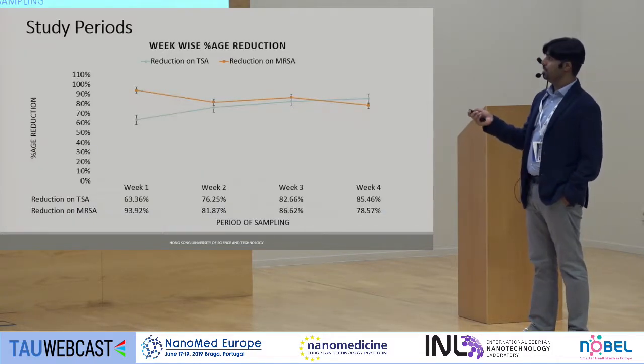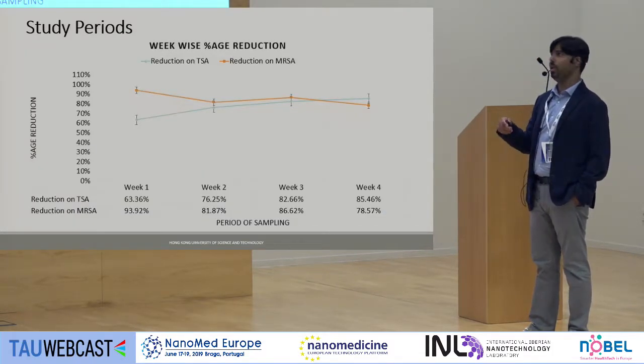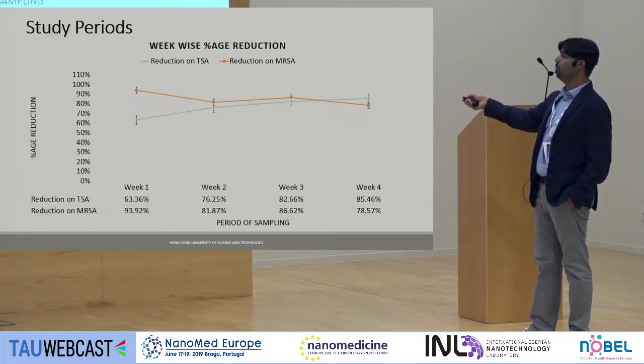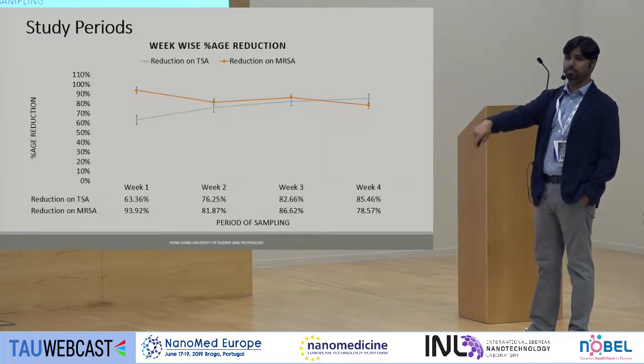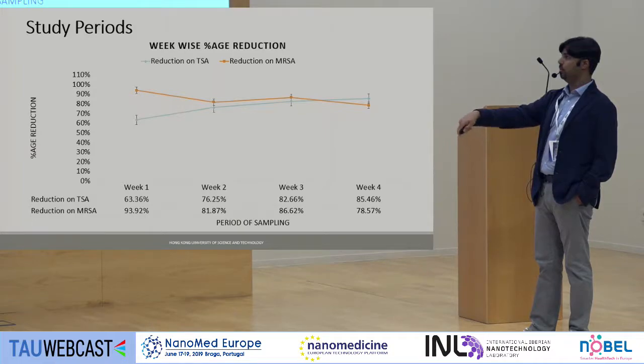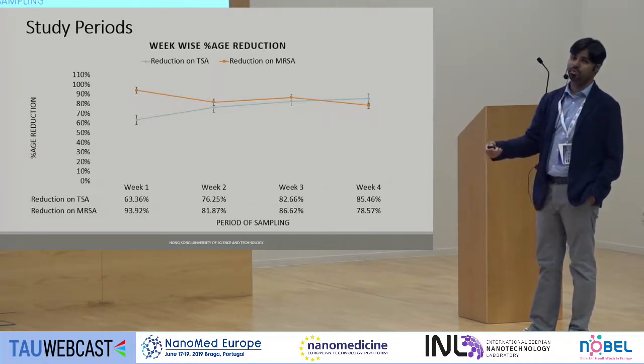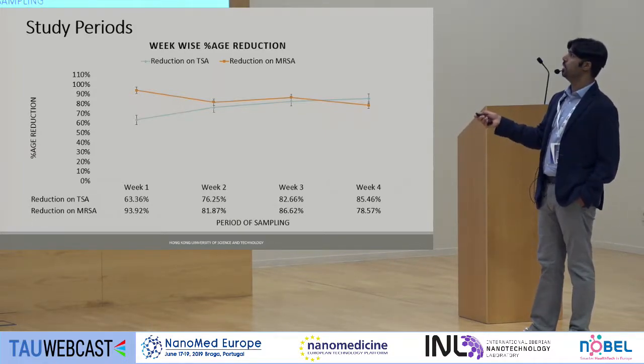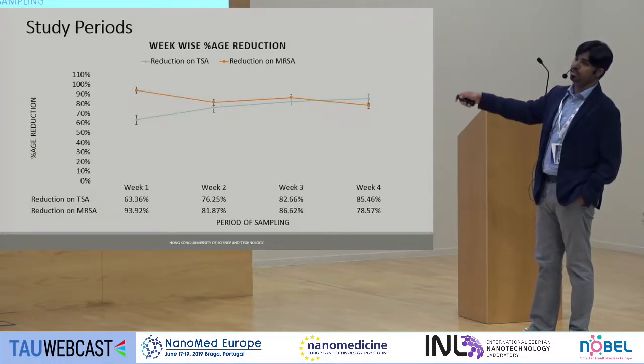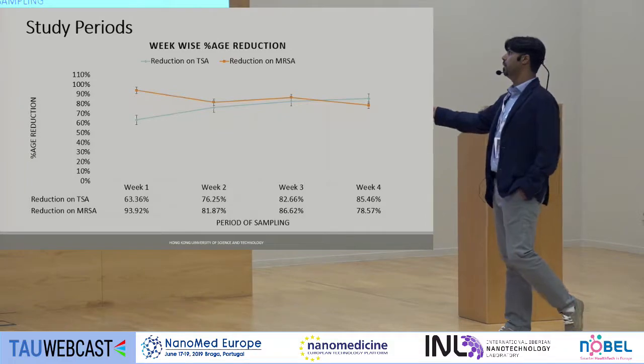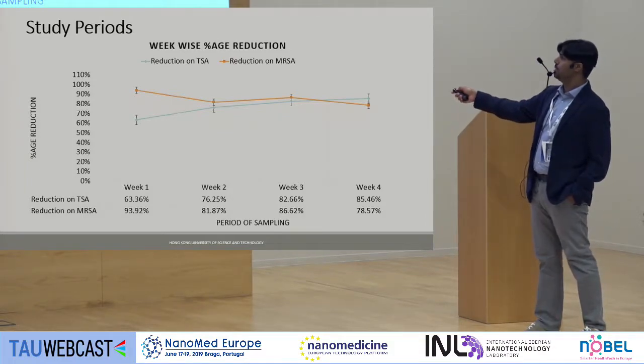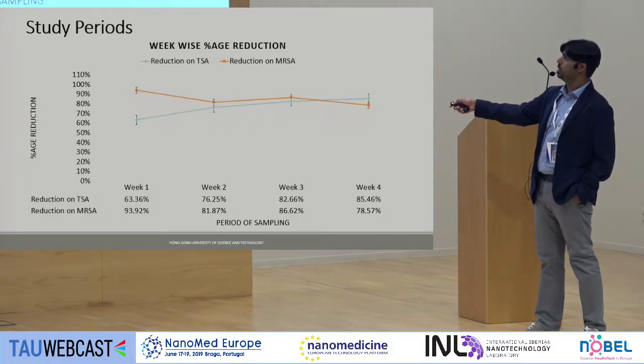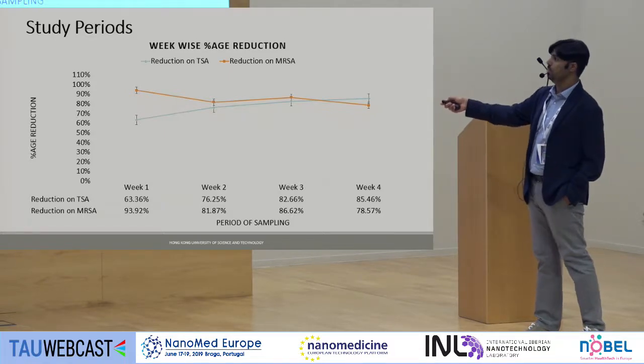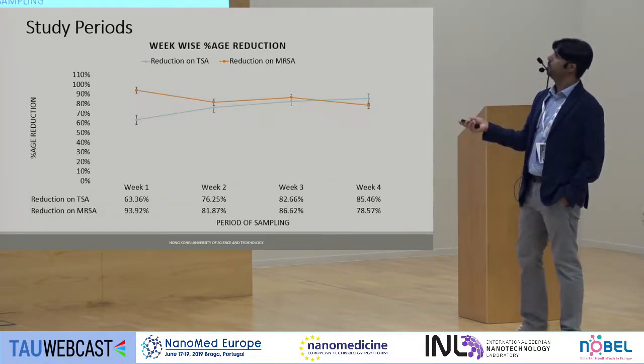So the consistency of antimicrobial efficacy we have tested for 4 weeks. Once we put it in the coating material, we did not change it for 4 weeks. Every week we took samples and checked how much reduction was happening on the treatment end. It has given us around more than 80% reduction. On this slide you can see the results.